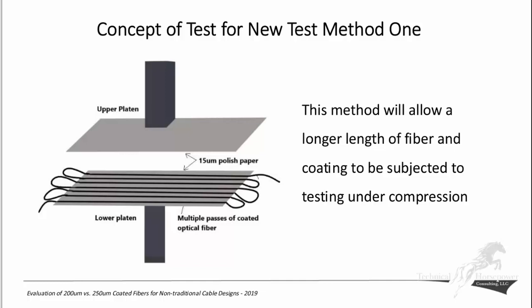So we came up with the idea of extending the platen from 10 centimeters out to 25, and instead of one pass, folding it back and putting 24 passes on that fixture. So now we have a 6-meter gauge length, a little easier to see some results. And we said we're not talking about a flat, smooth, shiny surface, but let's start looking at a coated surface, something that would simulate the size of the crystals in a water-swellable component. Again, we've seen a lot of variability. Sizes have varied tremendously from less than a micron all the way up to 50 micron in these crystals, and they're hard. So we have a concern there.